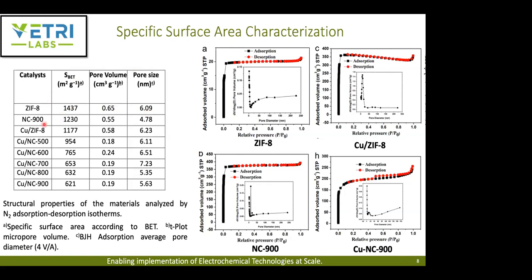And they're representative. And then when they do this copper ZIF-8, the porosity and pore volume decrease, the surface area decreases, and the nitrogen doped carbon has a higher porosity compared to the copper nitrogen doped carbon. So this tells us the copper NC and the nitrogen doped carbon have fewer micropores than the copper ZIF-8 and ZIF-8. This could be because of the collapse of certain structures inside the MOF. So that's why there is a decrease in micropores.